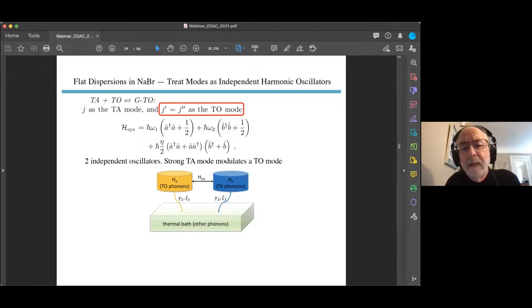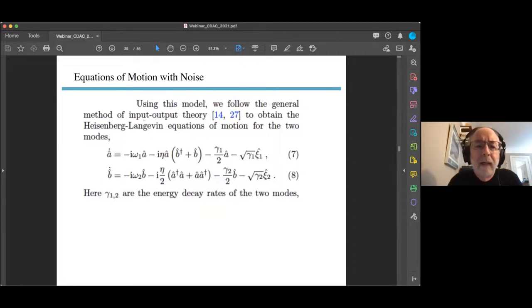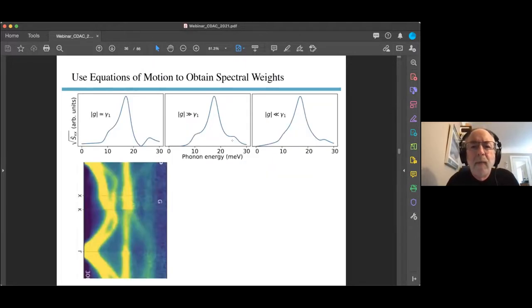We don't have a laser here. We have TA modes, and these are in thermal equilibrium. And so we have to take into account their noise, which is not done typically for the laser, but we can work with the Heisenberg-Langevin equations the way they do and look at the time dependence of these operators for the transverse optical and acoustic modes, which would non-interacting just be their frequencies. But we have an interaction with the other mode. We have an interaction with the bath, the noise bath, and we have a damping behavior here. And Yang Shen did work to calculate what these look like. In the medium coupling limit, we get a behavior that looks like this, where we get a sideband up here, which has got a gap, and the intrinsic localized mode, which is down here, is a lot harder to see.